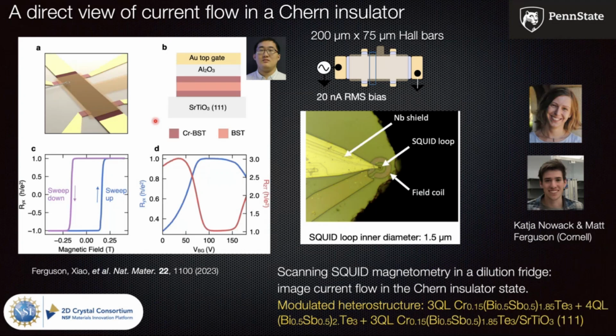And we said, "Sure, it should be a straightforward experiment." So Run Shao, my student, grew the samples and fabricated the devices, top and bottom gates and everything. These are nice devices. They're probably not at the standards that you need for metrology, but the quantum anomalous Hall effect is nicely quantized. The RXX dissipation is reasonably low, down to something like a few ohms or thereabouts.